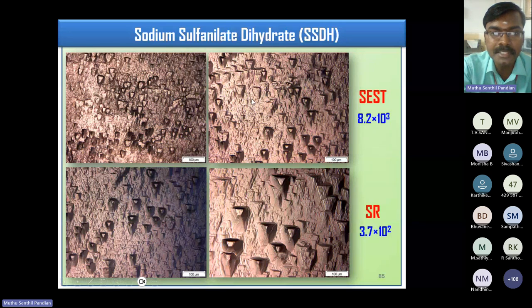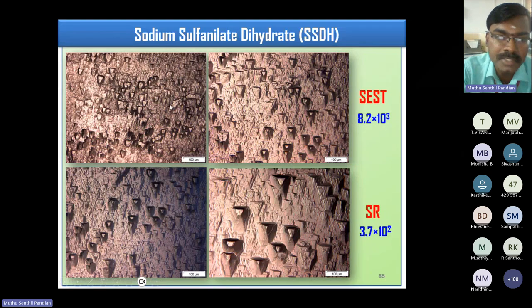The number of etch pits in the conventional method grown crystal is very high compared to the SR method grown crystal because of the large dislocation density and more microcracks, milky opaque regions, grain structure boundaries and so on. But in the case of the SR method grown crystal, there are no microcracks, no milky opaque regions, and less dislocation density.